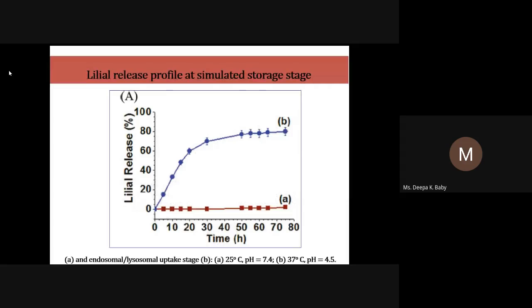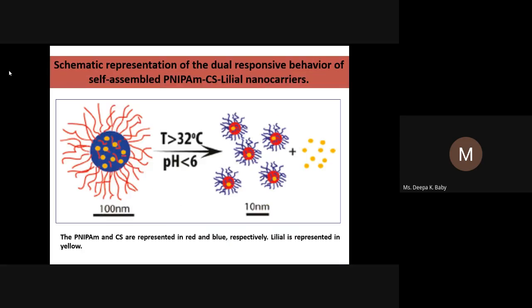So this is the Lilial release profile at two different stages. The red line shows the Lilial release at pH 7. Okay, at pH 7, there is no release of drug. Then when it is taken to pH 4, the size decreases. As a result, the drug trapped inside the micelle is taken out. As a result, you can see a release of Lilial from the micelle. And the mechanism of this is explained like this.